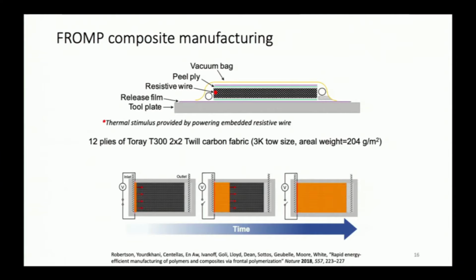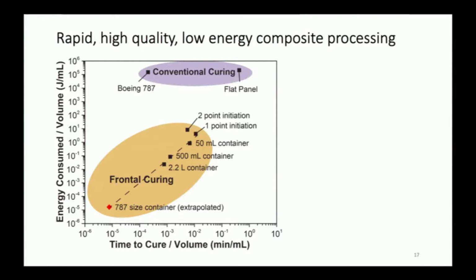We can use this frontal ring opening metathesis polymerization, or FROMP, to manufacture composites. Composites, as I said, are about 50% volume of plastic materials and 50% maybe a carbon fiber, for example, a woven carbon fiber. And so by this frontal polymerization, as you can see in the bottom diagram, we can infiltrate that with monomer and catalyst and trigger that initiation, and the front will travel in a very stable, regular way across that material. And as I mentioned, we've done some back of the envelope calculations to compare, as you can see, a typical fuselage section of that 787 by conventional curing.